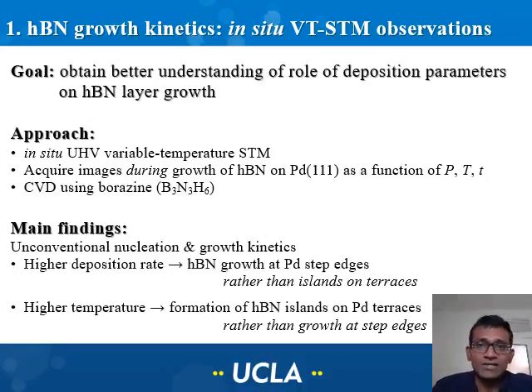we use ultra-high vacuum scanning tunneling microscopy both as the growth tool and as the characterization tool. All our experiments are conducted in situ in the same system. We first grow palladium-111 layers by sputter deposition in a separate system, and we clean it after we bring it into the ultra-high vacuum scanning tunneling microscopy system. And there we expose it to borazine, our precursor, and we collect scanning tunneling microscopy images as a function of deposition pressure, the borazine flux, and the substrate temperature, and the deposition time. And the main finding in our experiments is that we observe very unconventional nucleation and growth kinetics.